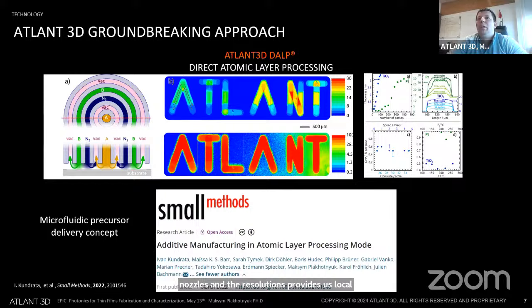And here you can see our first article published in 22, where each letter was deposited with different thicknesses. As you can see, a lot of artifacts at that time. We have already fixed many of them. And what we didn't expect is conformal and also very abrupt deposition, as you can see here from the lines of the process.